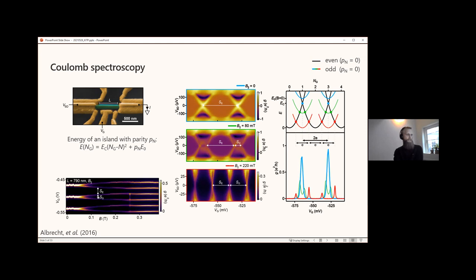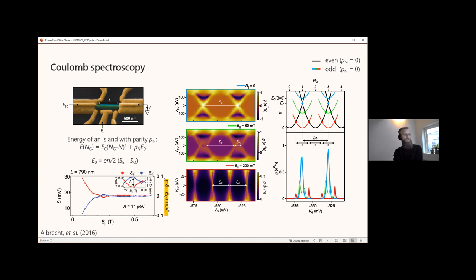And then we can call the spacing between the Coulomb peaks the even peak spacing and odd peak spacing. It turns out that the subgap state energy, the minimum of the odd parabola, is proportional to the difference of these peak spacings. And we can use those to extract the subgap state energy. So this seems like a slightly complicated way of measuring subgap state energy, but the resolution that you can achieve is much higher and is complementary to the tunneling spectroscopy. So these are the two tools that we use in the lab quite often to probe the subgap state energy